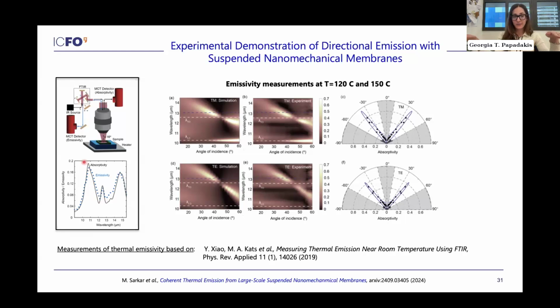And then we take it out of the microscope in order to do angle-dependent measurements, and here you can see the simulations and the experiments, and these all pertain to wavelengths that are close to the Reststrahlen band of silicon carbide, where its dielectric function is very high. And you can see that for both linear polarizations, we get these emission lobes that look like an antenna, except we don't even have a grating. We have a simple planar structure.